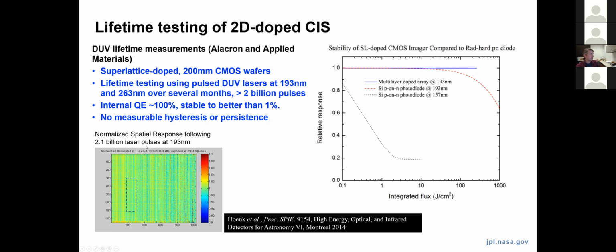flux of laser illumination. The same experiment was attempted on a delta-doped CMOS imaging sensor. I'm showing in the lower left here the normalized illuminated response of one of these devices after it was exposed to 2 billion of these excimer laser pulses at 193 nanometers. And the exposure happened only in this dotted region in the lower left here. So there was no obvious change in the responsivity of this device as a function of this exposure, as plotted here on the right.